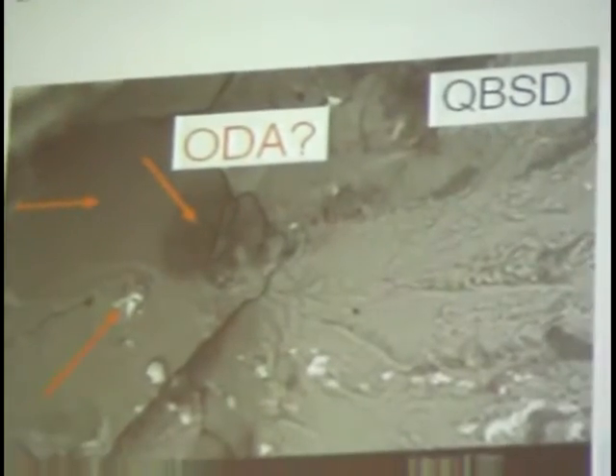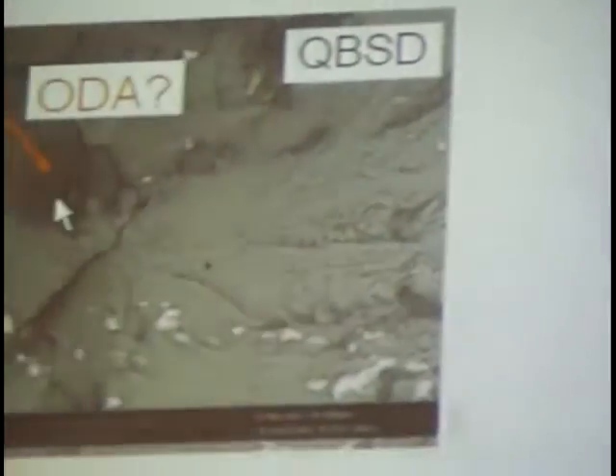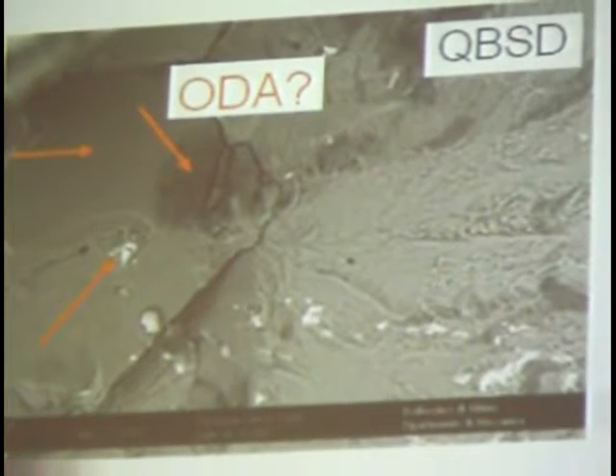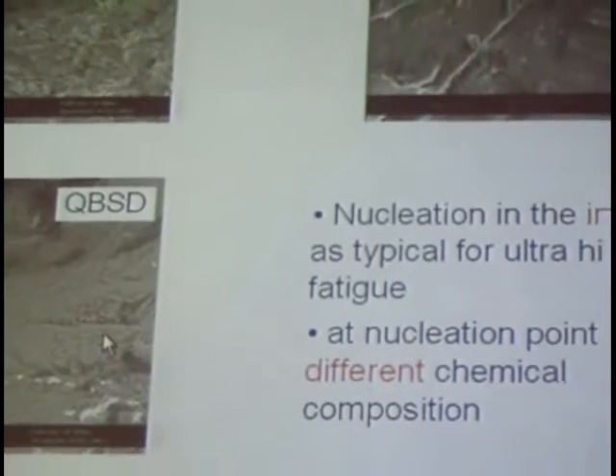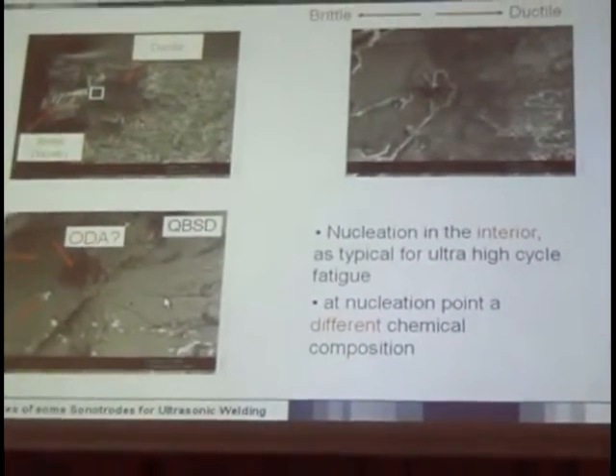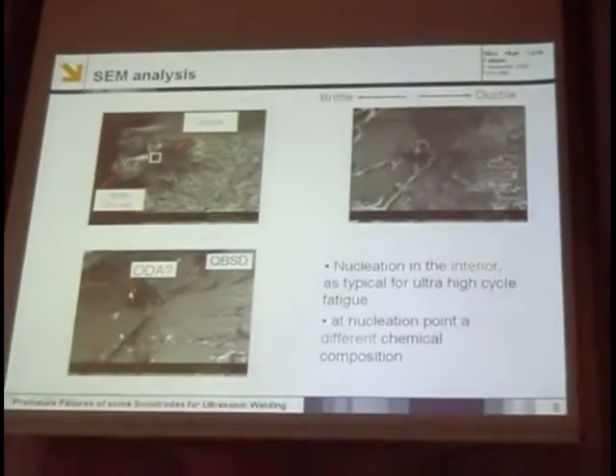We made an analysis of the initiation zone, as you see. Here, it seemed quite strange. We made a picture using the QBSD, the quadrant backscatter detector, with different diffusion of the electrons in order to see different colors for different materials. We saw this strange region here. But I would like you to remember this other region, because we will need it in a short while, on the left of this particular region. Here we have something that I think we could name ODA, exactly as Murakami does for steels. So here we are in aluminum, but I did some research, and someone also talks about ODA for aluminum. So I'm quite confident that this is really an ODA region.